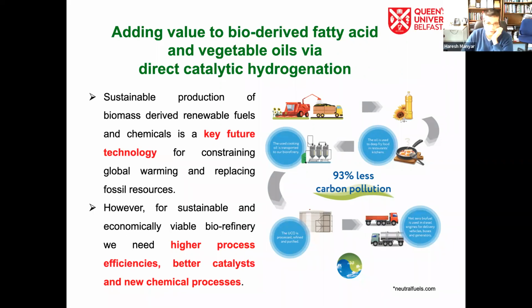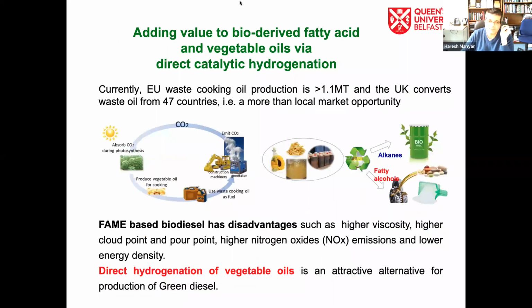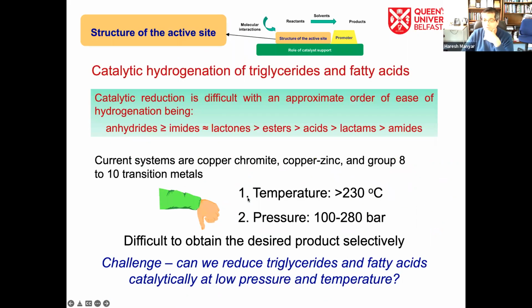the used cooking oil. So here what we do is we recycle the cooking oil. So we recycle the vegetable oils and convert them directly into the fuels. So that's the hydrogenation technology which we develop. Normally the hydrogenation of the triglycerides or the acids or this type of molecules is very difficult. It's very demanding. The temperatures required are 200, 250 degrees. The pressures required are 100, 150, 200 bars.